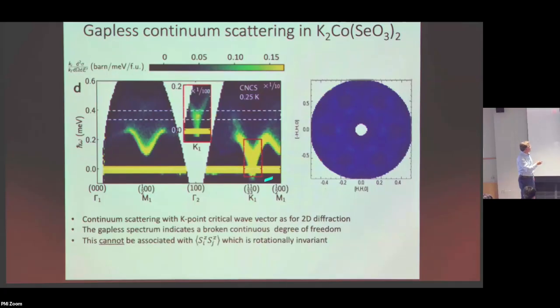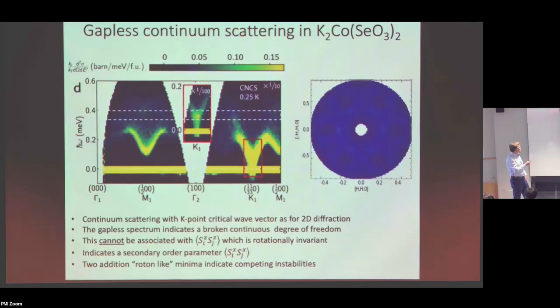Okay, so then I come back to this point of the gapless component, and what I want to say is that it can't be associated with the ZZ part of the correlation function because that's rotationally invariant, but it should be associated with the off-diagonal part of the planar projection of the spin, and so the presence of the gapless component indicates the presence of an additional transverse component in the order parameter. And these other features at the K half and the M point can be associated with roton-like minima that indicate other competing instabilities that are not coming to fruition in this material, but perhaps with longer range interactions, one could pull this mode entirely down and get some other kind of ordered state. So that's the basic story.